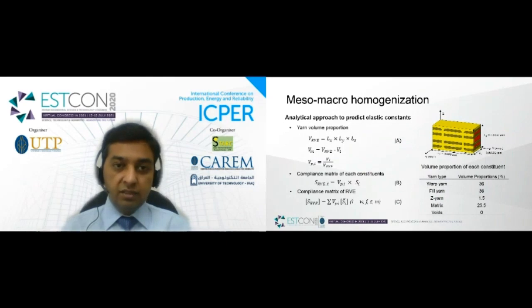The volume proportions which are estimated are summarized in the table. The RVE contains 25.5% matrix volume and 73.5% impregnated yarns volume, and it is assumed that there are no voids in the matrix. The compliance matrix of constituents was determined by multiplying their respective volume proportions with the compliance matrix given by equation B. Finally, the volume averaging method is applied to determine the compliance matrix of the whole RVE. Once we know the compliance matrix, we take the inverse to get the stiffness matrix, and from the stiffness matrix, we evaluate all the 9 elastic constants of 3D fiber reinforced composites.